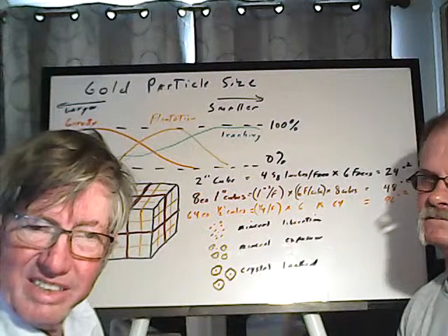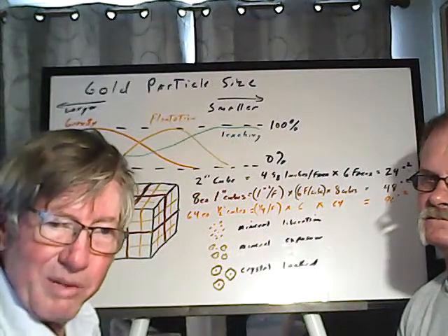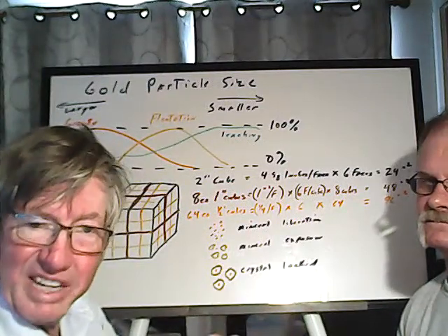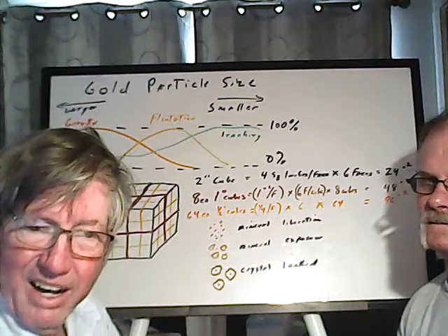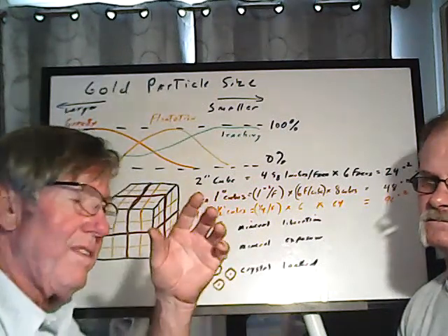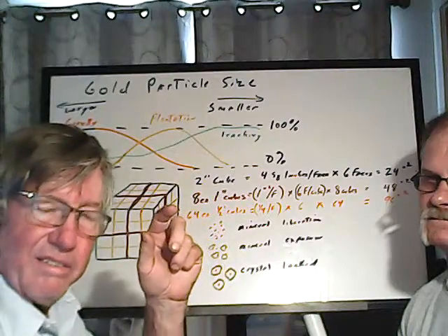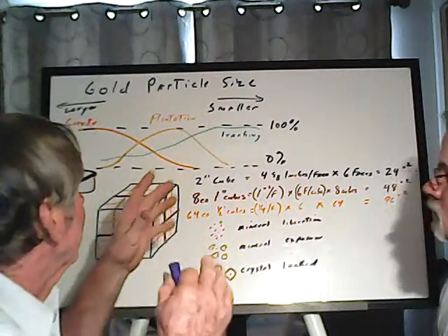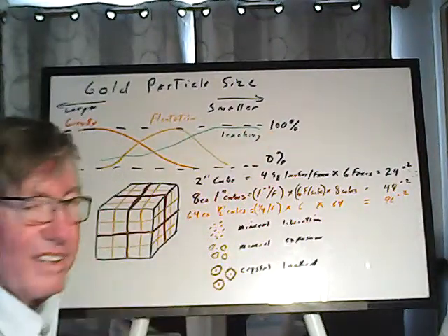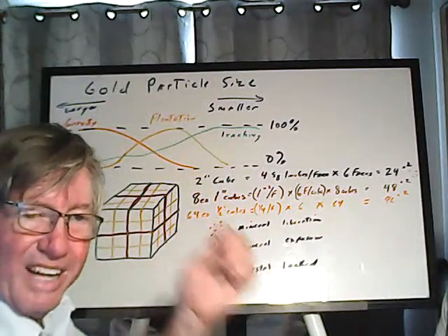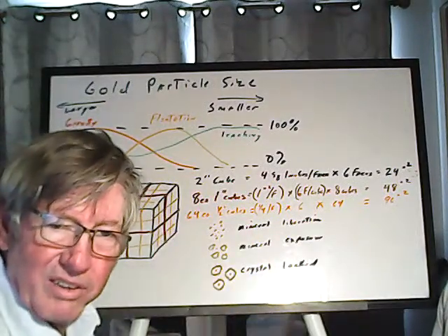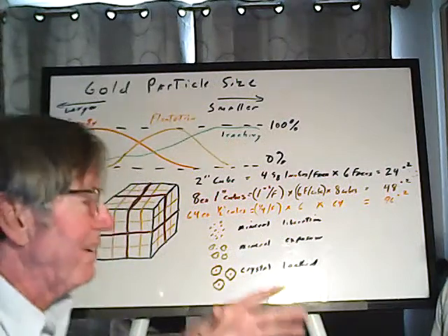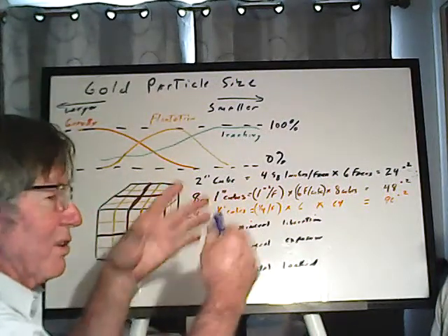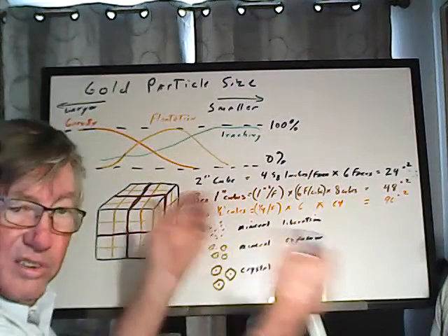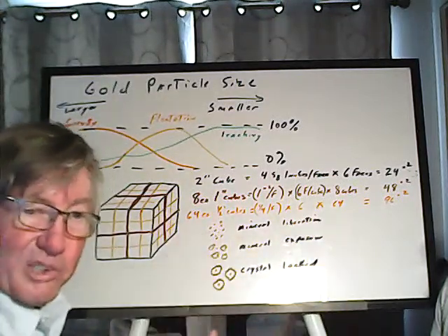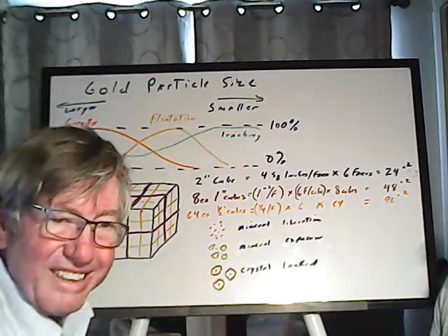David Reese says, how do you see 2,000 mesh gold with a microscope, or in our case, they used a scanning electron microscope. But in order to get the proper chemistry to work on leaching, the chemical has to touch the gold particle. Now, if you grind it to the point where all the gold particles are loose from all the rock particles, that works great, but you don't have to get it that far.